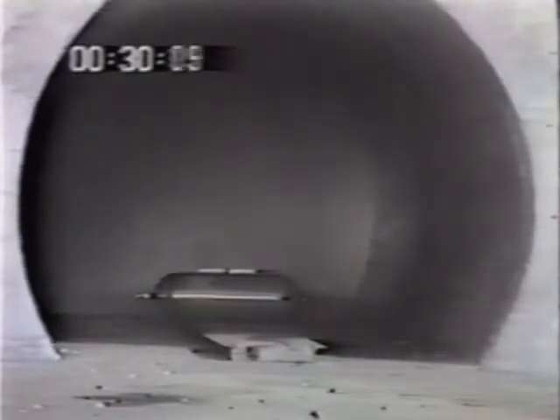This is energy equivalent to a car impacting a wall at approximately 89 miles an hour. It is particularly noteworthy in this test that while there is gas venting, it is venting through the valve and relief device. The blue arrow above the cylinder marks the spot where the dynamite was placed. What actually happened is that a shock wave from the dynamite, an instantaneous pressure spike on the order of 8 to 12,000 psi, created a deflection in the valve, causing the upper stem to move away from the seat and the relief device was ruptured.